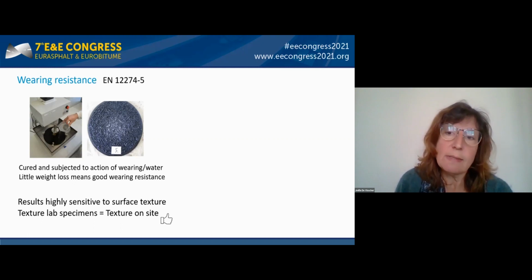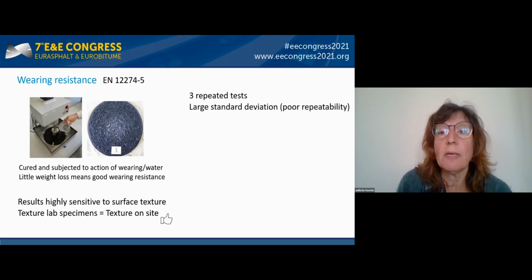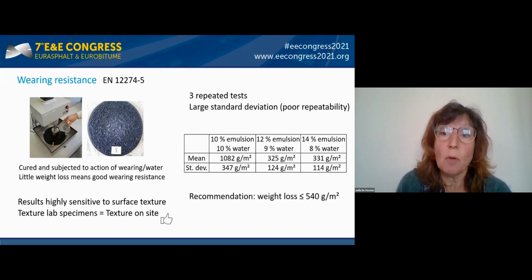The repeatability of this test has not yet been determined because of insufficient test data, but it's clear that repeatability is rather poor. So testing at least 3 specimens and discarding specimens with outlying texture is really necessary to improve the repeatability. But still, this test is capable of discriminating mixtures in a logical way. The result is highly sensitive to the amount of emulsion seen in this table, to the emulsion type, and to the emulsion aggregate interaction. And as for the interpretation, a maximum loss of 540 grams per square meter seems to be adequate.